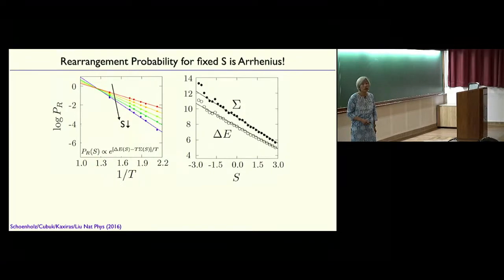That is, if you looked over a larger range at log P_R against 1 over T, whether there would be curvature somewhere. It does not seem to be. As long as we get adequate statistics, it really is straight, even in the aging system, even when we go below the glass transition. So it really is capturing the dynamics well enough to give us a well-defined energy barrier behavior.